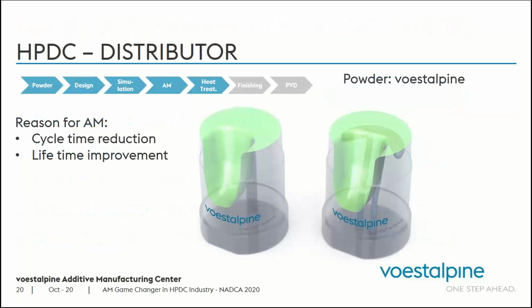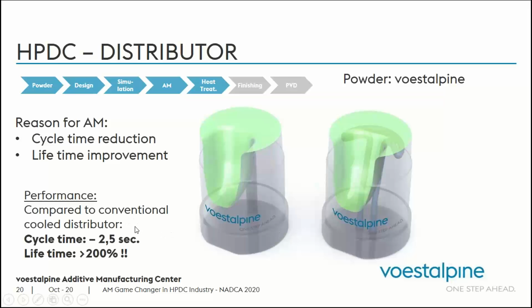I'll show you a couple of case studies from our group that we have been working on. For the one in front of us right now, the distributor, we used the powder from voestalpine, and the target of applying additive manufacturing was cycle time reduction and lifetime improvement. As you can see here, how complex the internal cooling channels are inside. After 120,000 shots of this specific application, we were able to get a cycle time reduction of 2.5 seconds and lifetime improvement over 200%.